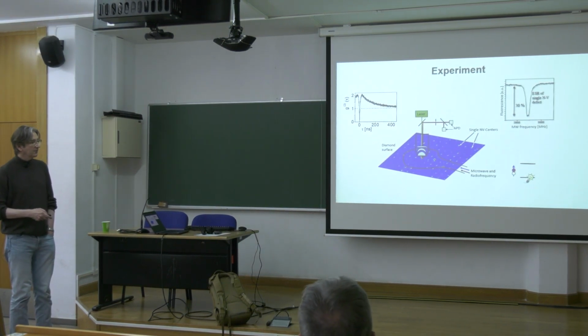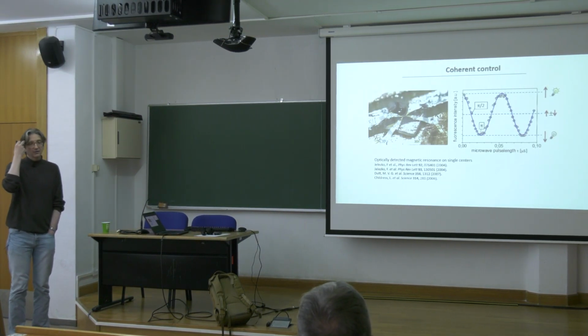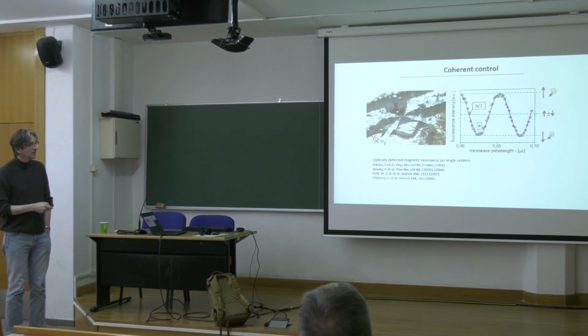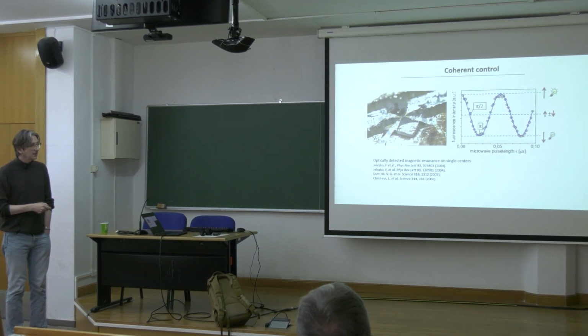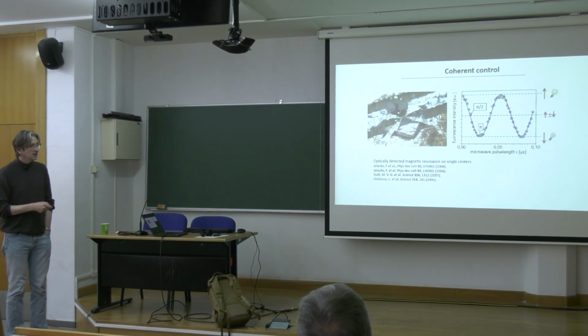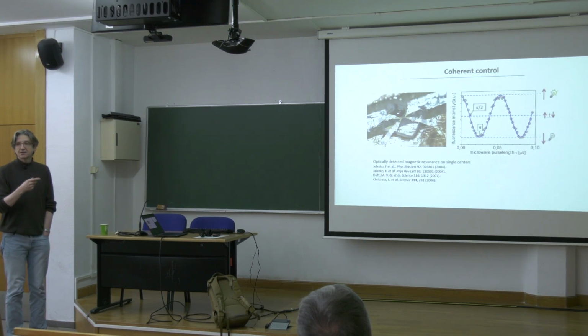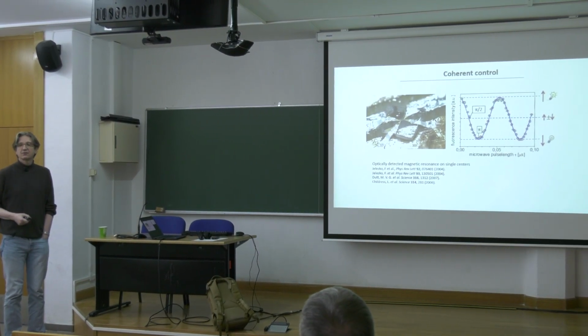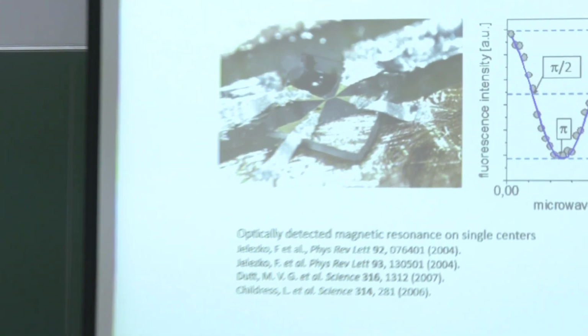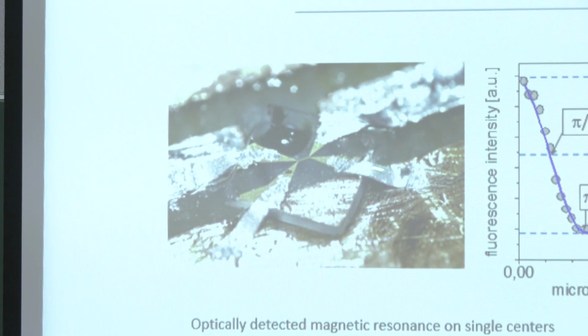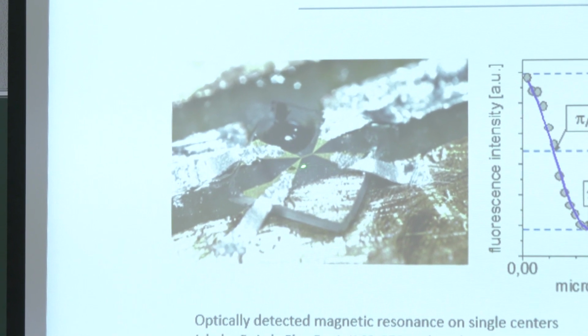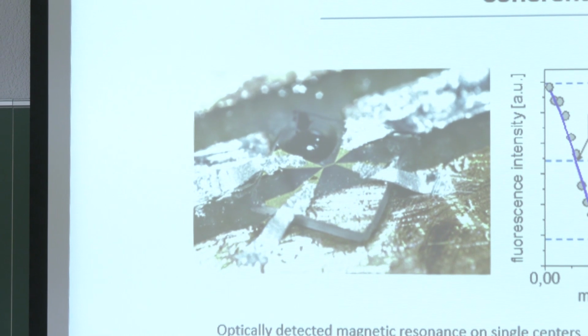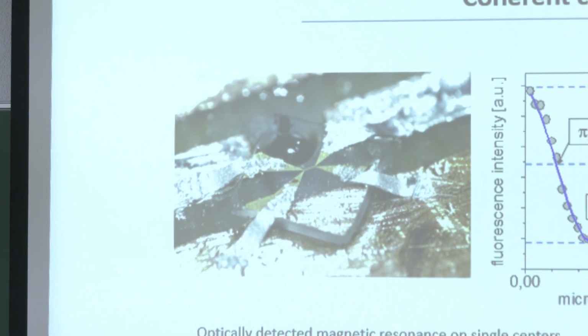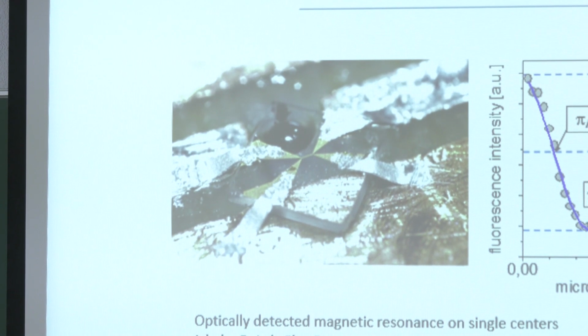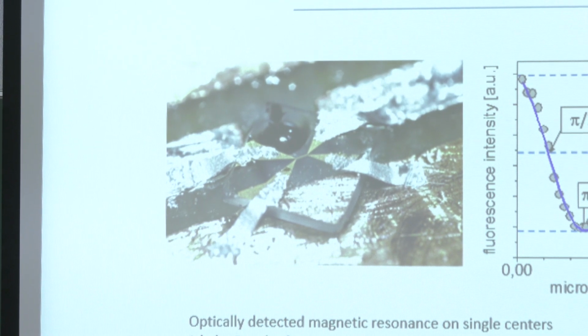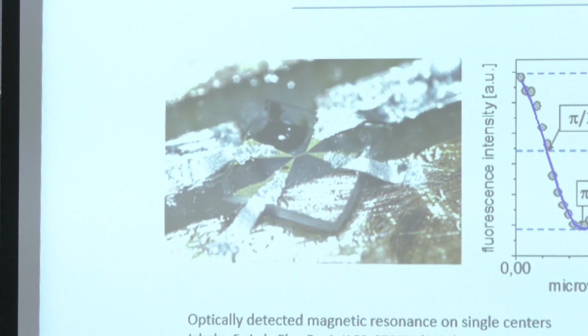This is a scheme of the experiment. I also show you the heart of this experiment in the photo here on the left. It's a piece of diamond where we deposit a microwave antenna. It's not a resonant antenna. It's not emitting microwaves. It's actually a near field effect. We are passing microwave current through it. The distance here between this narrow part of the waveguide is about 10 to 50 micrometers, and the NV centers that are used in these experiments are implanted in this region.